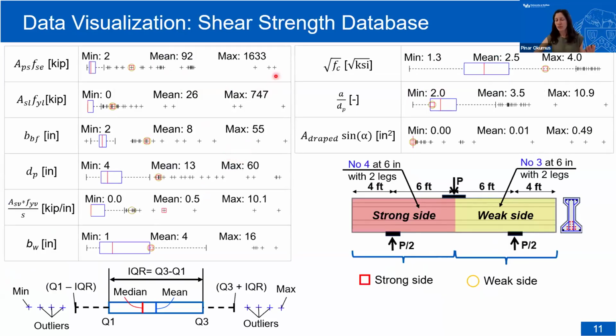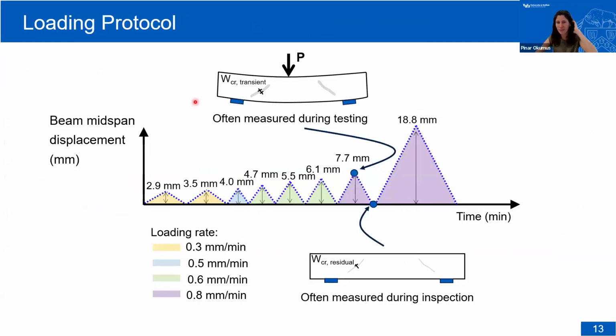If you're wondering how the new data we collect compares to the 804 beams that are out there, these box plots show that. Most of the available data in the literature will be in these boxes. The plus signs are the outliers, and the colored circle and square are our beam, with the 2 sides of the beam. What is apparent here is that our beam is an outlier for the most part, and that's because most tests in the literature are actually pretty small size. Our 30-inch beam is a fairly large size for this data set, with heavier reinforcement as well. So it is new data compared to what's available.